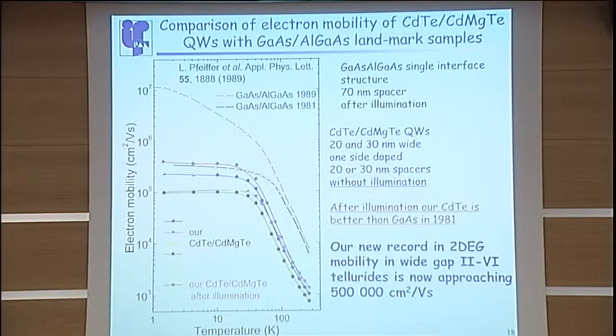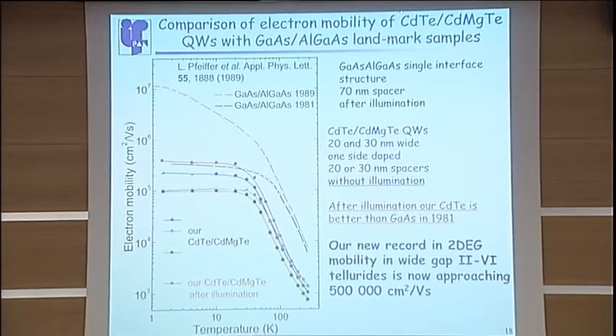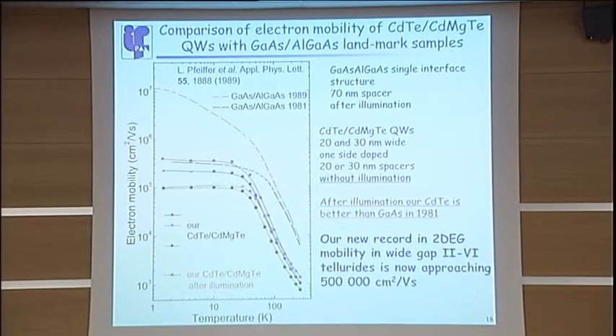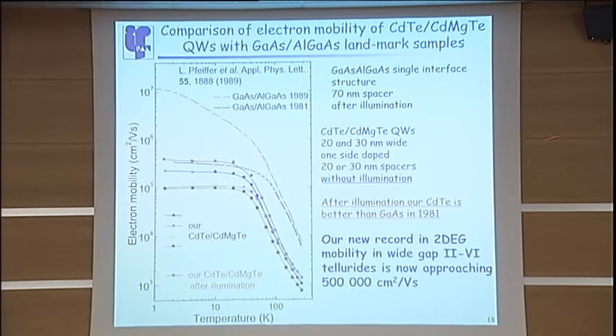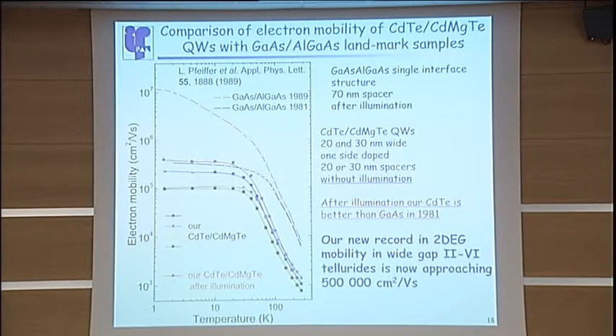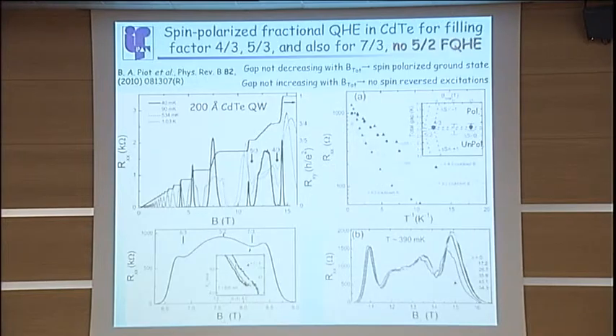So where are we now? It's presented on this view graph, where I have plotted results for landmark samples in the gallium arsenide history. I did not put recent achievements of the mobility of roughly 40 millions, not to get too disappointed, because you can already see that our structures are still far behind those produced by gallium arsenide people. With our mobilities of 500,000, we are roughly in 1981 in comparison, so there is still a far way to go. But nevertheless, even this quality of the structure made a qualitative progress, because we could observe